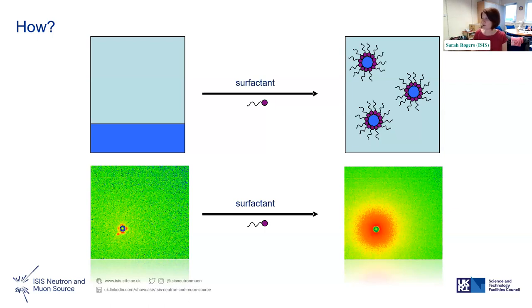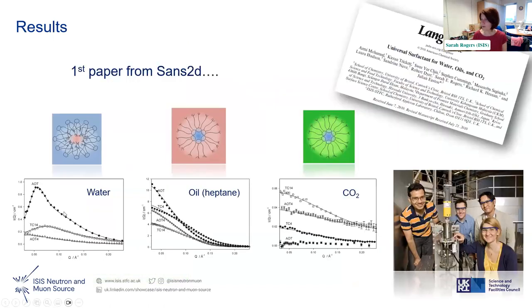So that's the kind of the image. That's what we had before. Then we add the surfactant, you get these nice nanodrops. And what that looks like from a scattering perspective on the raw detector images, you get basically nothing. And then when you add the surfactant, you get some clear scattering around the beamstop. What we then do is we can do the radial averaging.